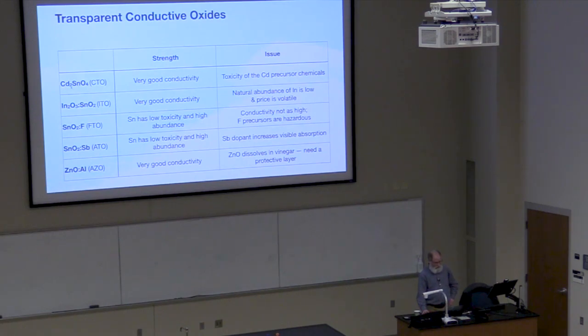One of the best materials is cadmium tin oxide, cadmium stannate. And you see, in the business, everybody has these little 3-letter initials, right? So CTO, very good conductivity. The problem is cadmium is pretty toxic. This material itself is not; it's stable. So that's okay, but from my point of view, when you see how we make our coatings, any residual cadmium from the precursors that we might use, or maybe in the exhaust system, would be an issue.